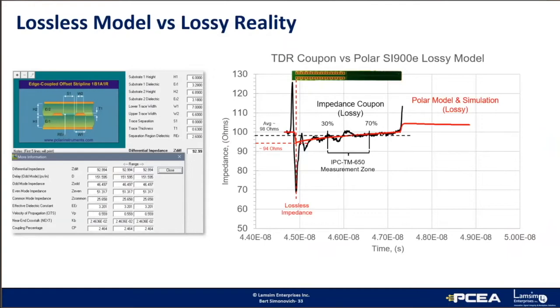Resistive loss often results in a slow monotonic rise in the impedance profile, as shown here. IPC TM650 specifies the measurement zone between 30 and 70%. Most fab shops will measure an average impedance over this range, but the true characteristic impedance is at the beginning of the TDR plot. And in this example, for a lossy dielectric, we see there is a 4 to 5 ohm difference compared to the true characteristic impedance depending on where the measurement is taken.